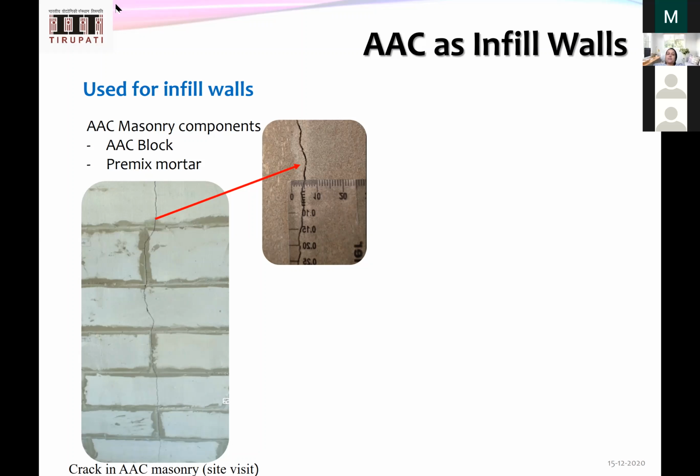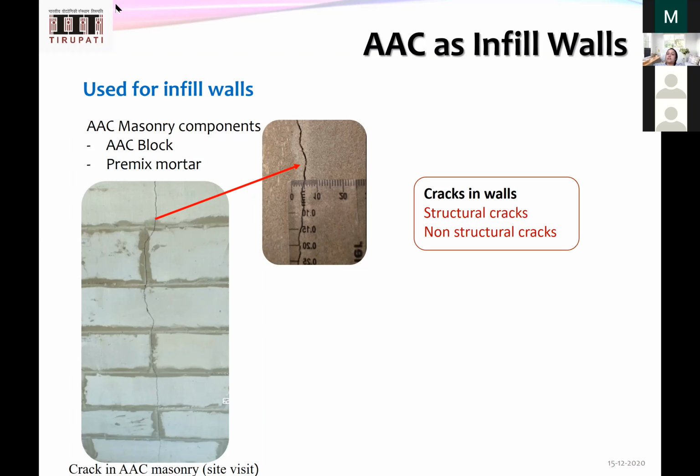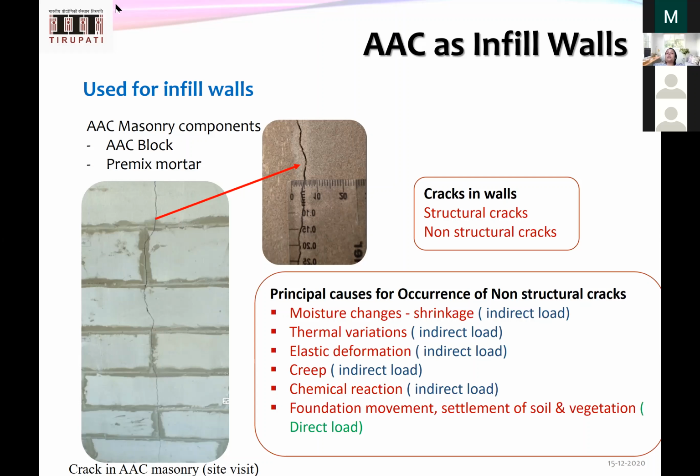In AAC masonry blocks, if you see these cracks, as it is an infill wall, it is not a structural crack. Normally we define cracks as structural cracks and non-structural cracks. So this could be a non-structural crack; it is not taking any load. For a non-structural crack, different causes are possible. There could be a moisture change, because of which you can have shrinkage. You can have thermal variation. In Tirupati, the temperature variation is in the range of 40 to 50 degrees, sometimes going to 50 degrees in the month of May. When Kerala gets a good rain, here we are in oven condition.